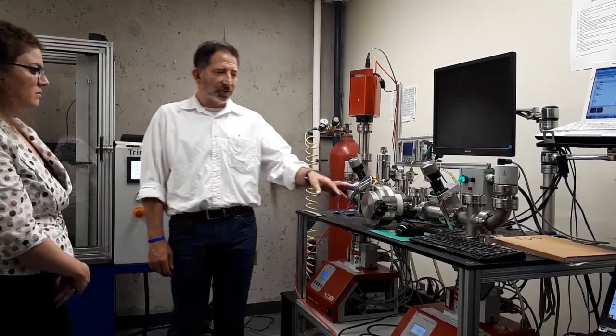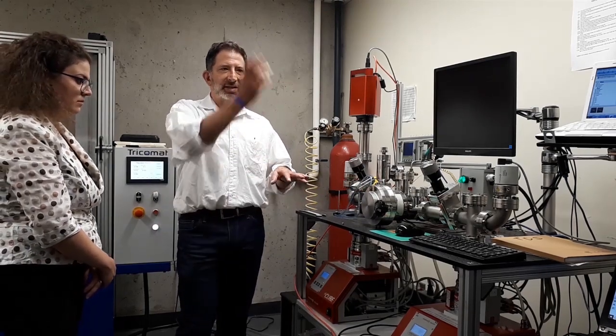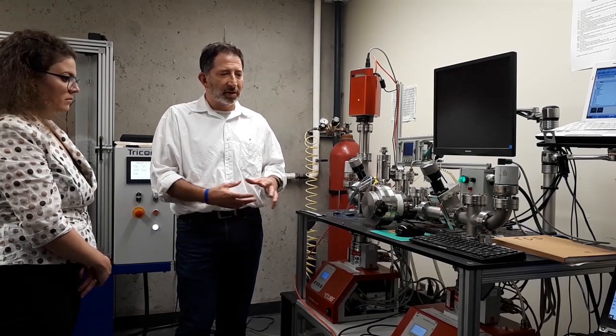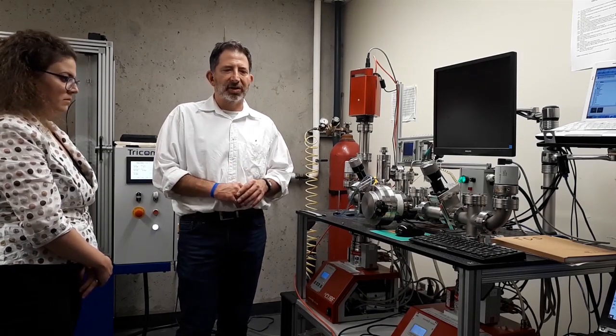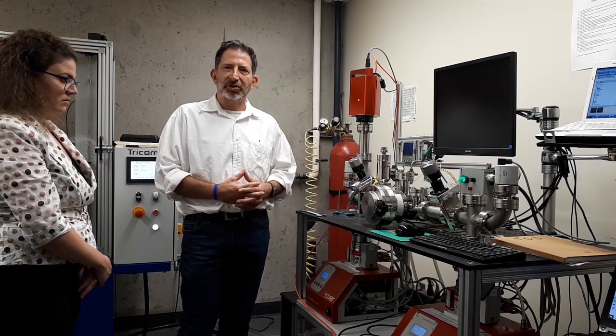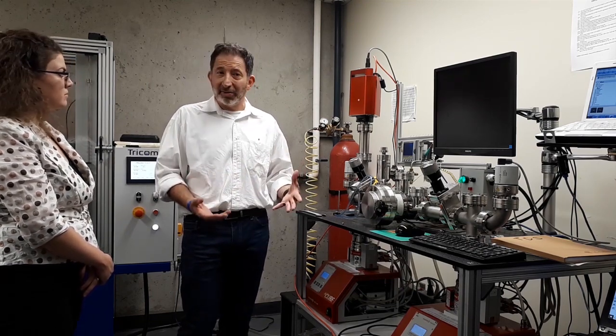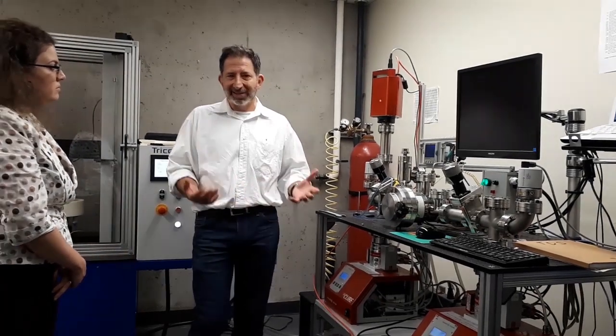Depending on the temperature at which we heat it, we see that more hydrogen comes off if we heat it more, and so the temperature correlates with the energy of the trap site, so we can establish how much hydrogen is coming out of it. Now, why does this matter? Because hydrogen in high-strength steel in particular causes it to become brittle when the steel is under stress. We can do a lot of mechanical testing to see how much strength or ductility the material is losing, but to correlate that with the actual amount of hydrogen, we need apparatus that helps us quantify the hydrogen. That's what the TDS does for us.